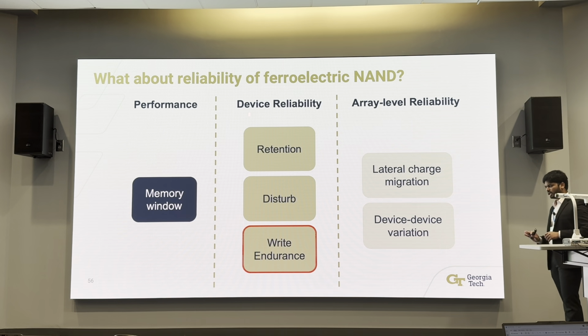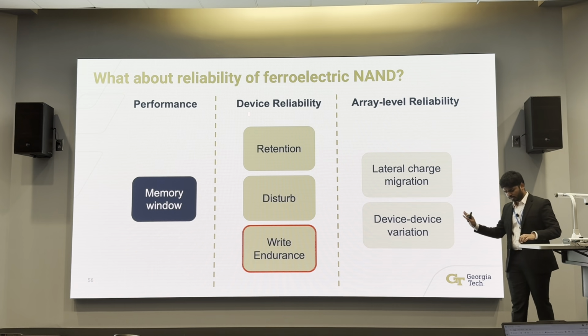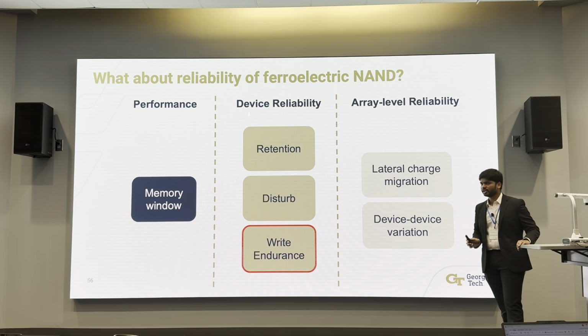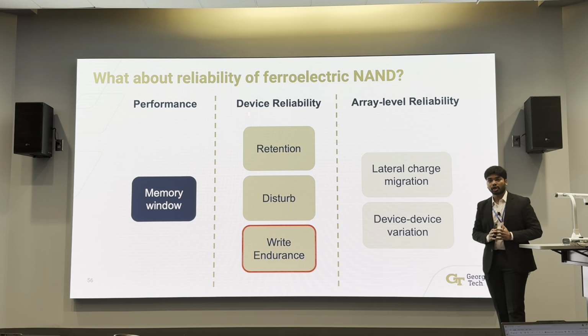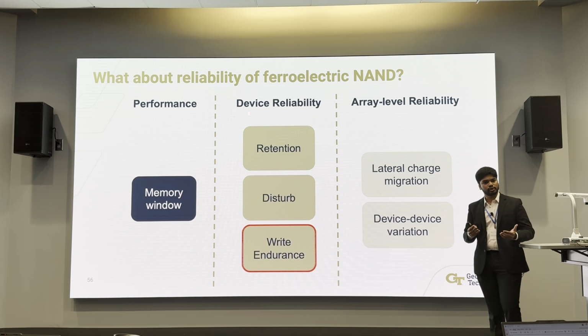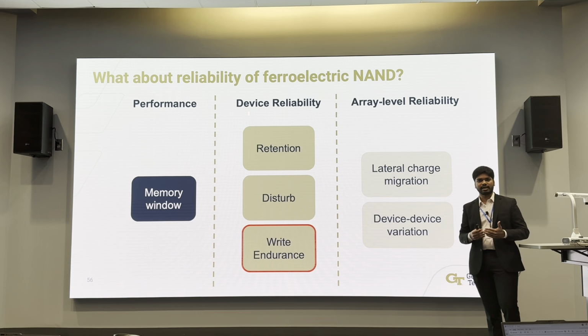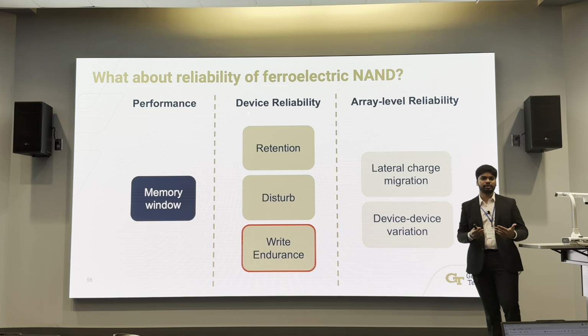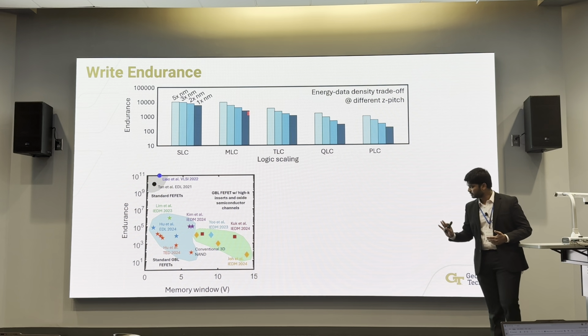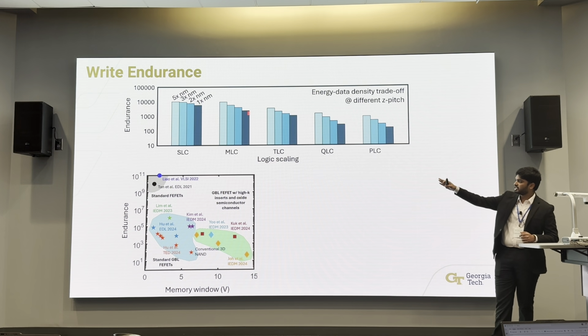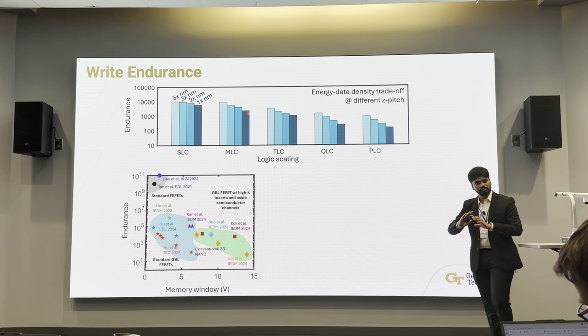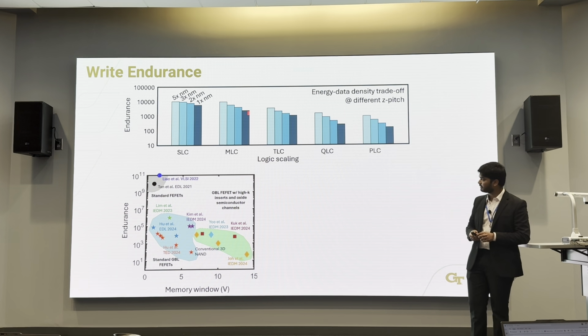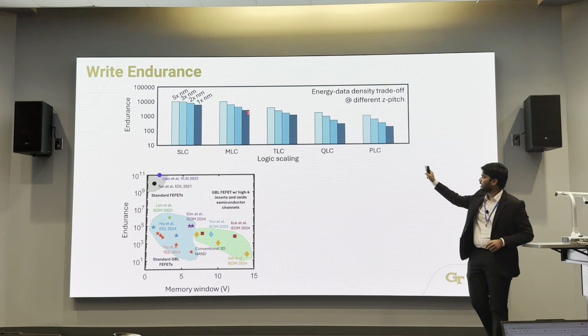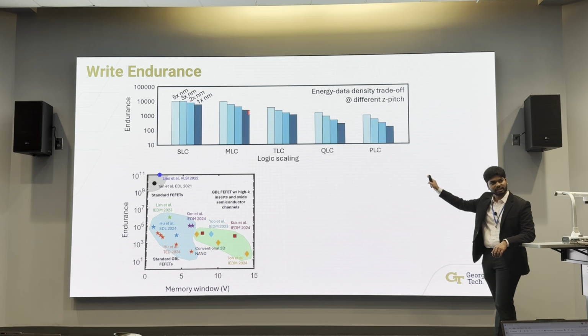So the last problem that I will not go too much into the detail is write endurance. Write endurance, though, we don't require 10 to the 12 or 10 to the 15 write endurance as we require in DRAM. In NAND, we require close to 100K to a billion write cycles. But still, we see that in SLC, MLC, TLC, and QLC NAND, in standard CTF NAND, as we go to higher and higher logic levels, the endurance degrades significantly.